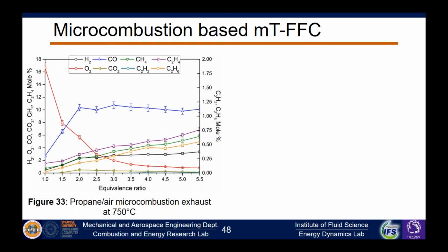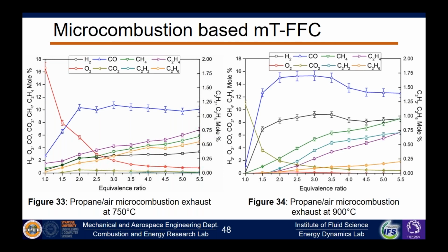Hydrogen concentration was even lower, but you notice that the process of converting propane down to syngas goes through these steps, and it's kind of interesting to see here. We have fairly high ethane, acetylene, and ethylene, these C2s. Propane breaks down first into the C2s. Those C2s then progress into methane and ultimately hydrogen and carbon monoxide, and then they go back to carbon dioxide and water as they're oxidized. So at 750 degrees, the resulting syngas isn't actually that good.